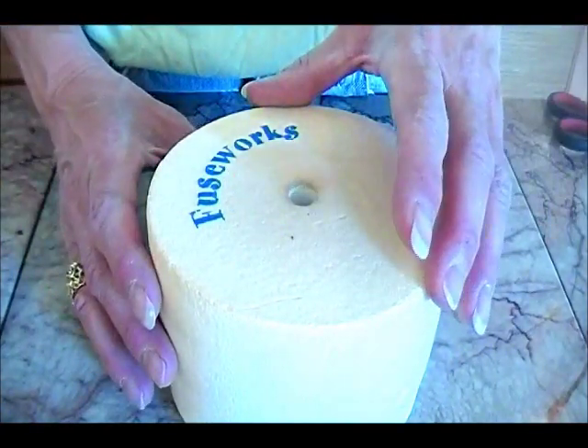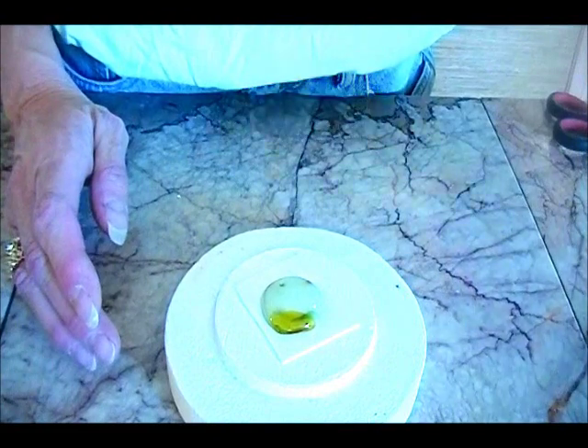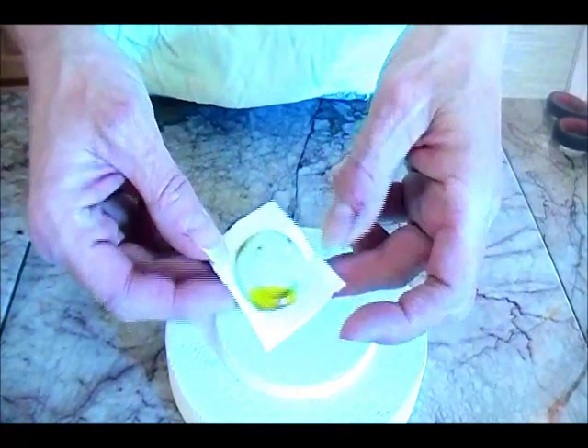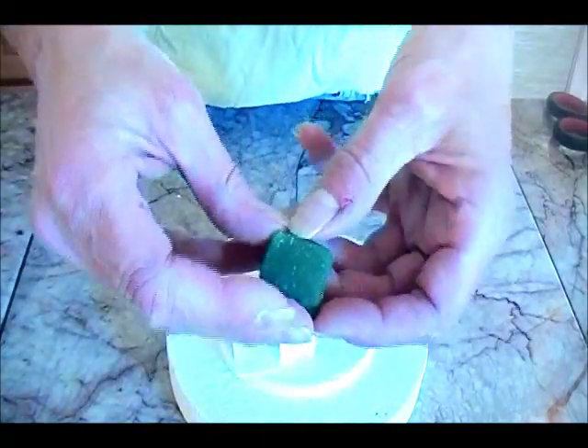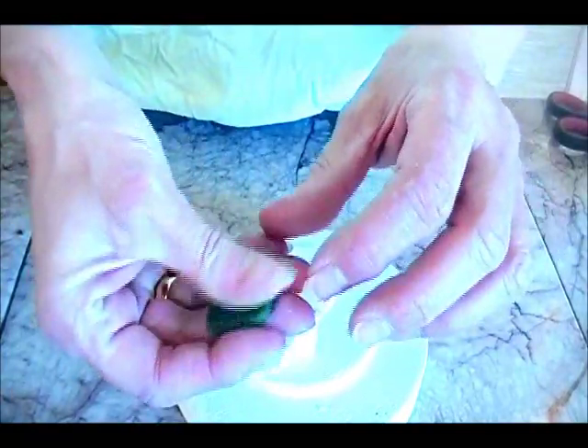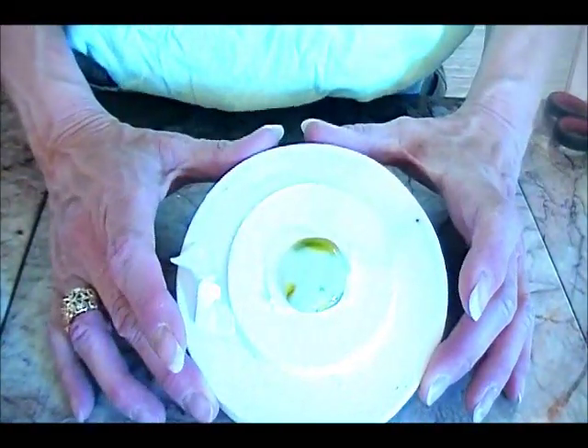It's been over an hour and I just glanced at it when it was still glowing red hot and the shape was really good. The cab is still really hot. The millefiori melted completely in, and this fiber paper does wash right off - I washed it right off the back. The glass is really rough - it just takes on the texture of whatever it's sitting on, so if you don't like that you'll have to grind it down. But I like this shape. The color is a little weird but it kind of looks natural. It's still really hot after over an hour - this thing really does a good job at annealing.